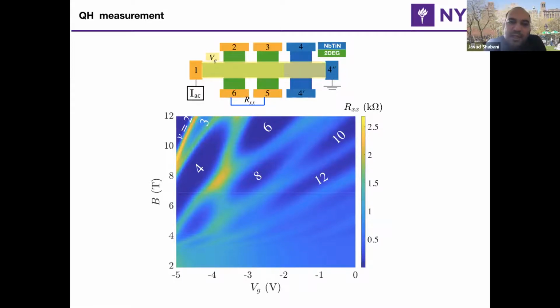So what I'm showing you here, the schematic is shown on top. So basically we are sending current from contact 1, a normal contact, to 4 on the right side, which is basically a superconductor. We sink the current there and we measure 6 and 5, which are normal contacts, right? We see the behavior that we expect from a quantum Hall system. If I sweep magnetic field on the y-axis and sweep the gate voltage or density on the x-axis, you basically go through these quantum Hall states and the zero resistance basically says that these are well-developed states.